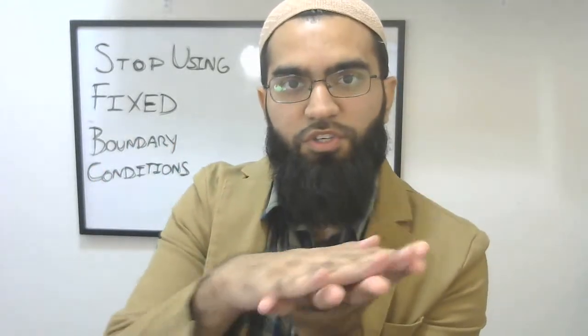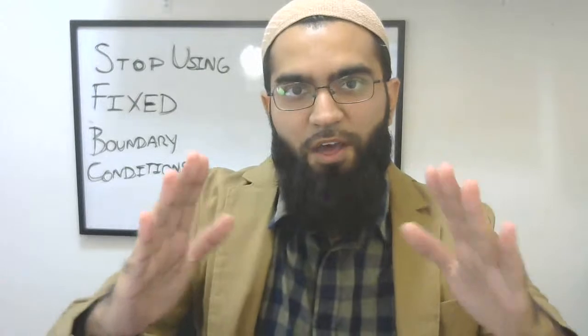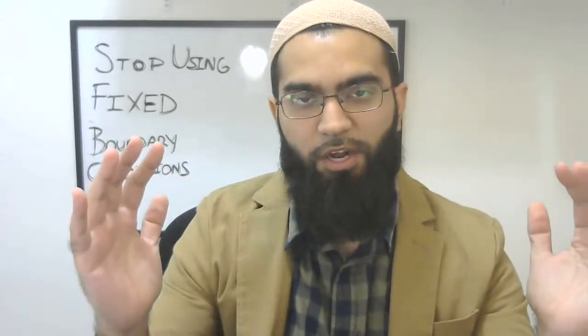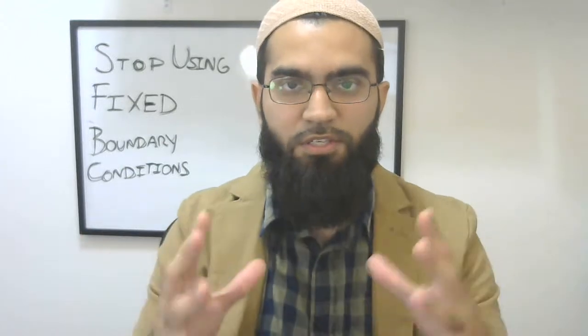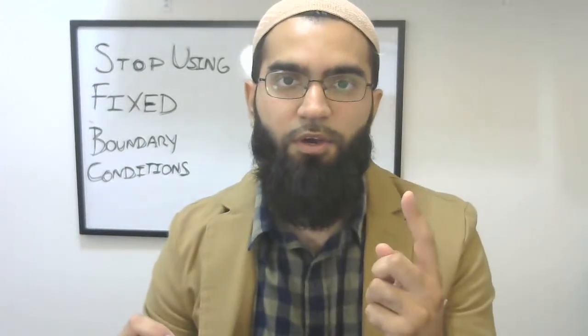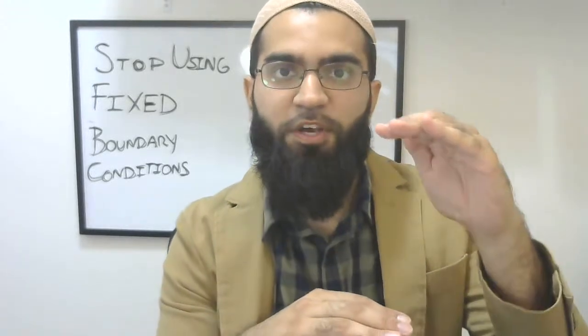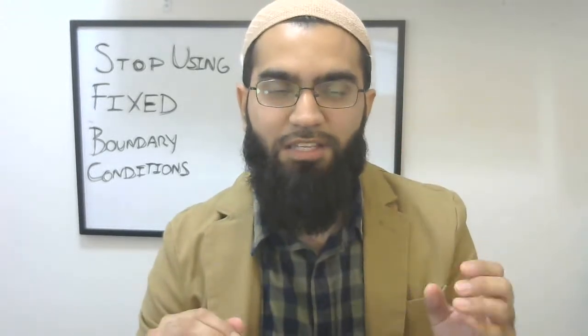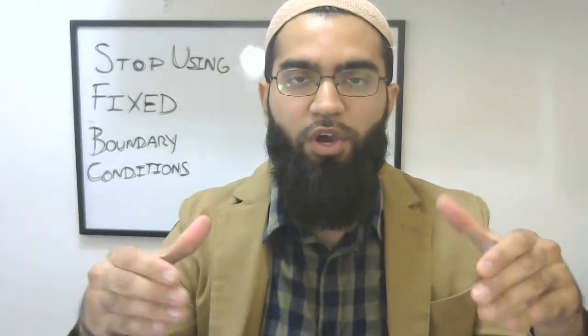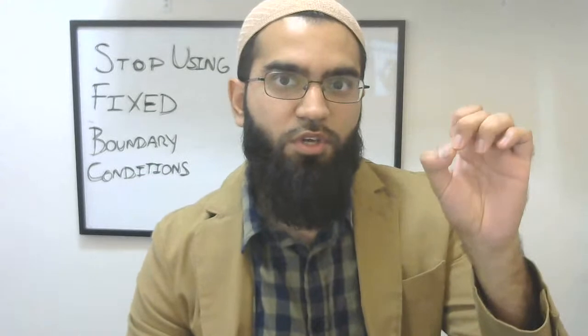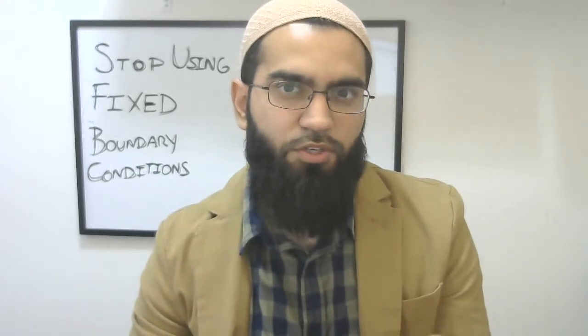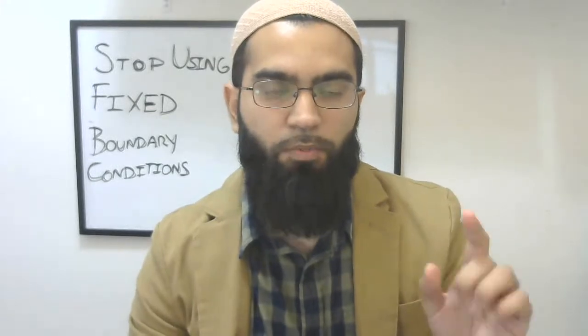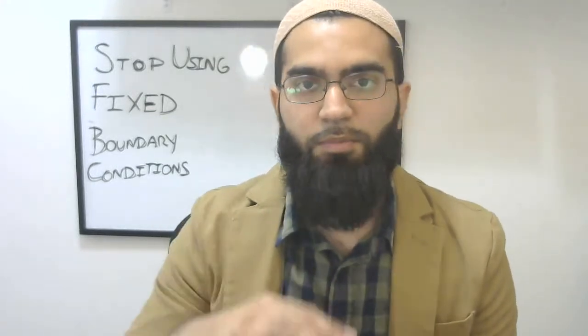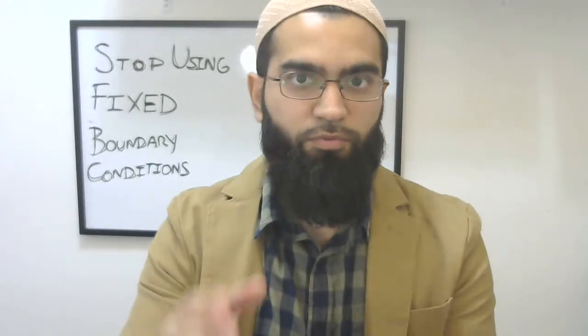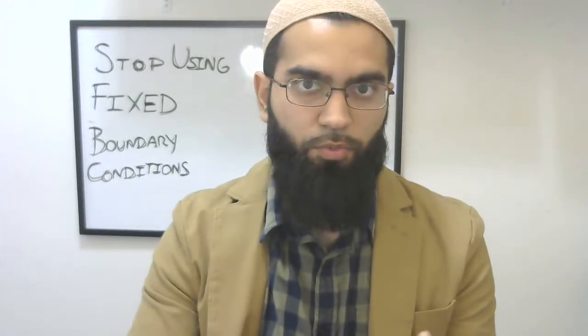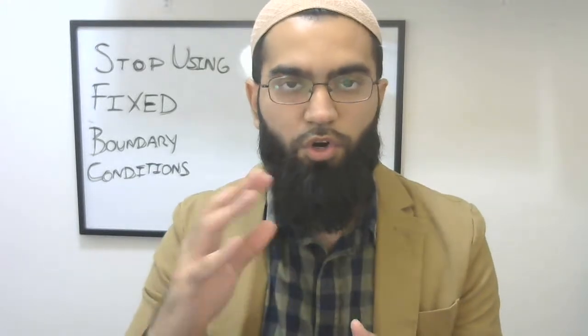However, you fix that boundary condition on the bottom, and it will then resist that outward motion, that outward flow of material. And that resistance actually stiffens up your disk, and it causes a lower amount of displacement to occur in the thickness. So in effect, you added another constraining equation, because that force to voltage conversion assumes something about the stiffness. It assumes something about how much strain will happen in the material as a result of applying that force, and hence it's going to generate that charge, which is related to the piezoelectric charge coefficient D.